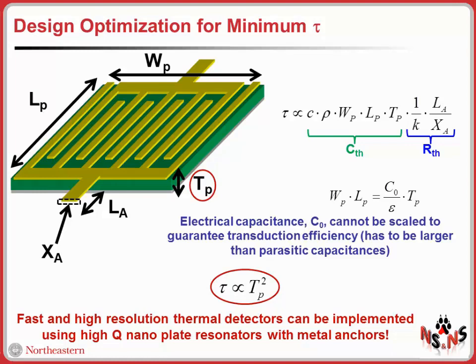So in order to scale the volume of the device while maintaining a pretty much constant value of electrical capacitance, which sets the impedance of the device, what is really key is to scale the thickness of the piezoelectric layer. So basically, that's why we like to call this device a nanoplate resonator, because that's really a key feature that enables a lot of sensing capabilities. And in fact, high-performance resonant thermal sensors can be really implemented using a high-Q nanoplate, which is basically anchored to the substrate using these tiny metal anchors.